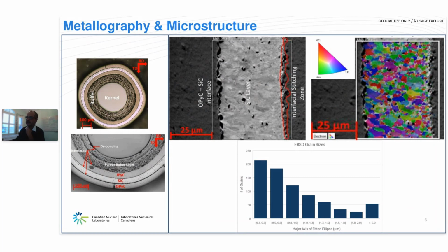Post-polishing, we look at the metallography and the microstructure of the polished samples. What you see on the top left is a low mag image of a polished cross-sectional image for the particle. At the bottom, you see these different components. What we see is that there is a bit of debonding between the kernel and the porous buffer layer, and sometimes we see some cracks in different parts of layers, constituent layers of the particles itself.